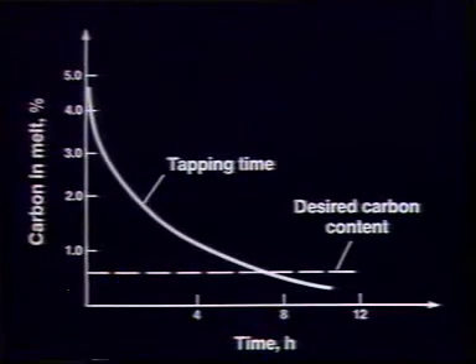Does the reaction stop? The answer is no, it doesn't. Because in his whole operation, he has put iron oxide in the system, which is dissolved in the iron, and it takes time for the cake to cook. So the iron oxide is reacting with the carbon continuously, and when it's tapped out of the furnace, he still has iron oxide mixed with the material. And it's still going to effervesce, give off the gases.